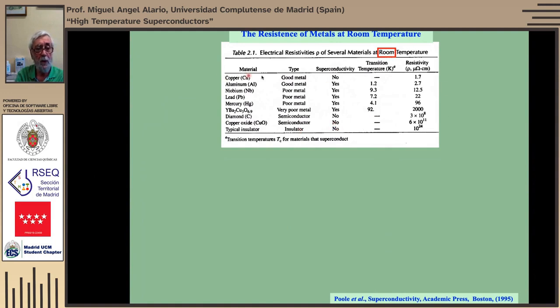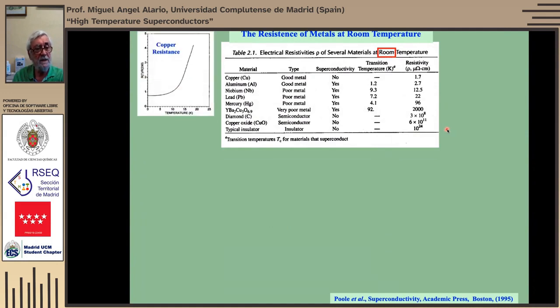So we go from copper, which is in micro-ohms, to an insulator which is 10 to the 24, which means that resistivity is a property, but that's the copper resistance. And resistivity spans 25 orders of magnitude, which is a very wide margin. It's not the same to measure this resistivity than to measure this resistivity. You need a different instrument even.